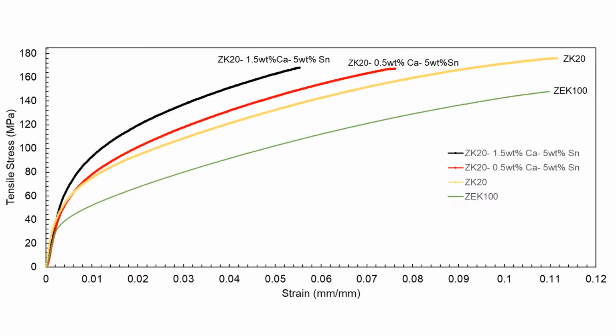Out of the different alloys that were tested, the 2 alloys with 5 weight percent tin gave better results for the tensile test. We were able to increase the yield strength when comparing it to ZEK100. However, as it can be seen in the graph, the elongation decreased significantly.